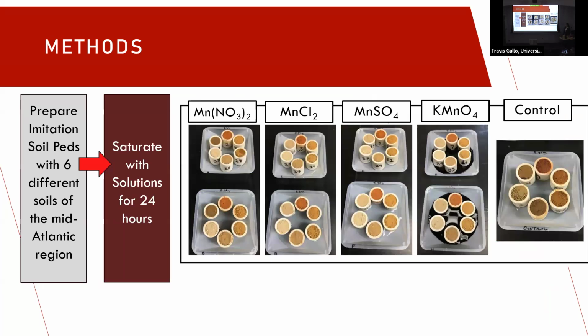So next, we saturated these imitation soil peds with laboratory solutions for 24 hours. We used manganese nitrate, manganese chloride, manganese sulfate, and potassium permanganate. We also had a control with just water. Manganese nitrate, manganese chloride, and manganese sulfate all have manganese in +2 form, where in order to form the coatings, the manganese has to oxidize. However, in potassium permanganate, manganese is in +7 form, so it actually has to reduce to +4 to form the manganese coating. So it's a little bit of a reverse.